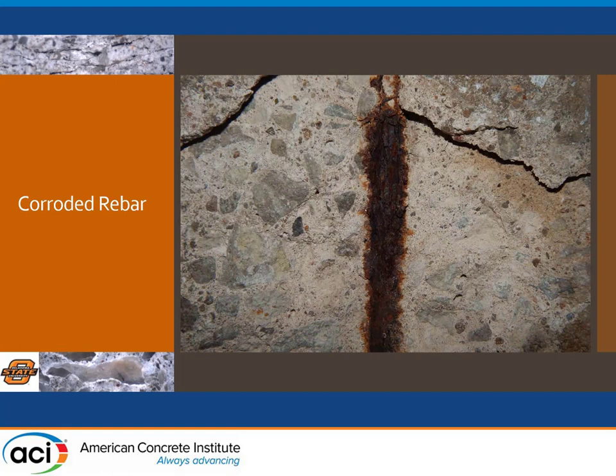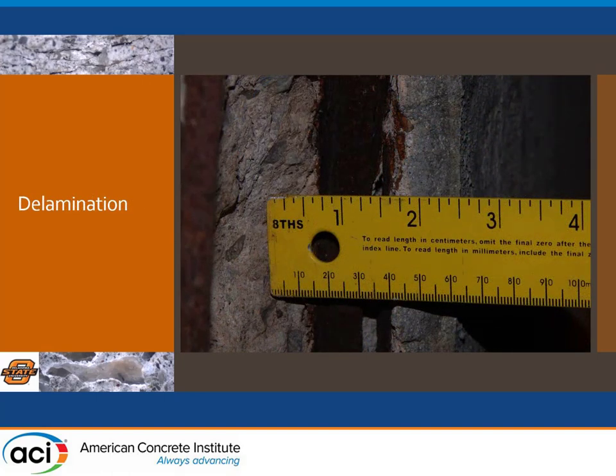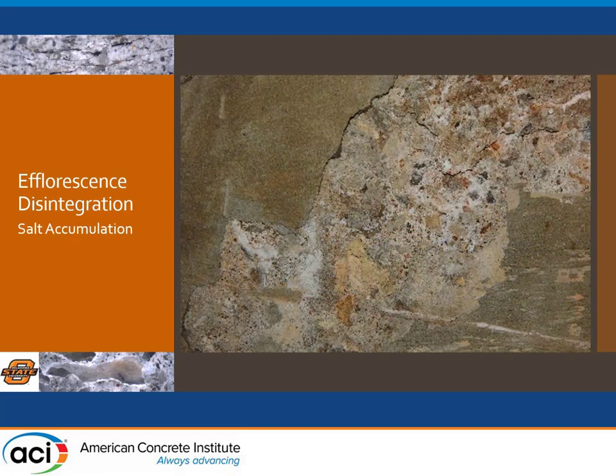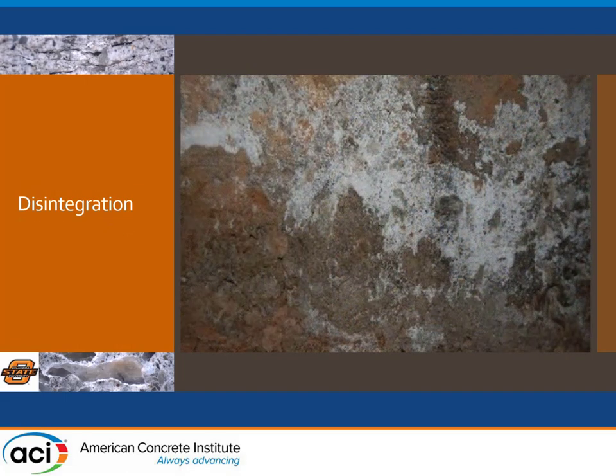We can see the corroded area, with whitish salt crystals all around it. The rebar was roughly at about one inch in cover, but the delaminated areas came right behind that rebar at about two and a half inches in — this is where all of the salts were accumulating behind the first rebar mat. As the scaling progressed, we're also looking at delamination, with white salts accumulating. It was more prevalent at the bottom of the walls in the buried section, and that's when we started saying: maybe this is an interesting case of sulfate attack.